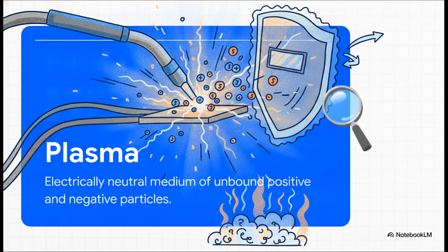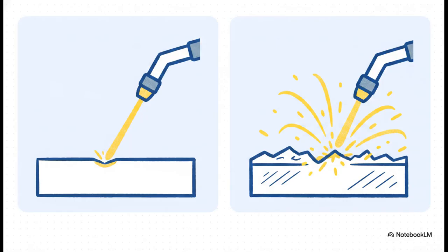electrode to the workpiece. This extreme environment uses a constant current power supply to create an arc, which literally turns gas into highly ionized plasma to melt the metal. The shielding gas, usually argon or helium, steps in to replace the air and protect that weld from atmospheric contamination. It's wild. You've got moving charged particles generating an electric current right inside a magnetic field, creating this pocket of intense, highly localized heat. And TIG gives operators unbelievable control over this plasma.